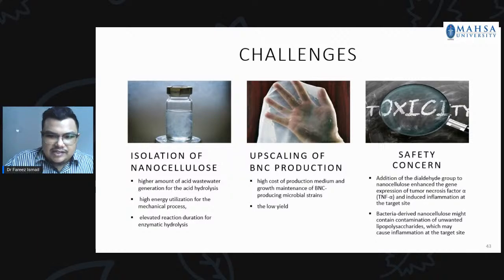It requires high energy utilization for the mechanical process, and can cause elevated reaction duration for the enzymatic catalysis. And one of the other challenges is how to upscale the BNC production, because the upscaling of the BNC production requires high cost in the production media and the growth maintenance of this bacterial cellulose producing microbial strain. And it can produce a very low yield.